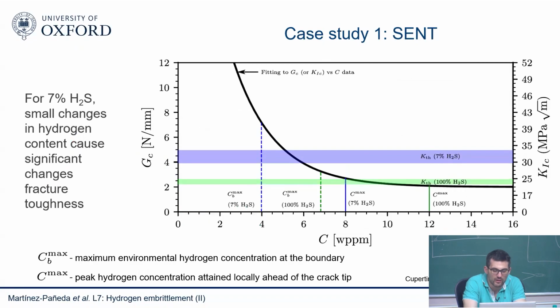And then what we find out is that if you look at the toughness versus hydrogen concentration data for these materials, and then we look at the hydrogen concentrations that you get at the boundary and at the tip of the crack, because we don't know where we must be, somewhere. So for the 7%, we move between here and here. For the 100% hydrogen sulfide (H2S), we move between here and here. So what you see is that there could be small changes in hydrogen concentration as a function of time and as a function of the effect of this corrosive layer.